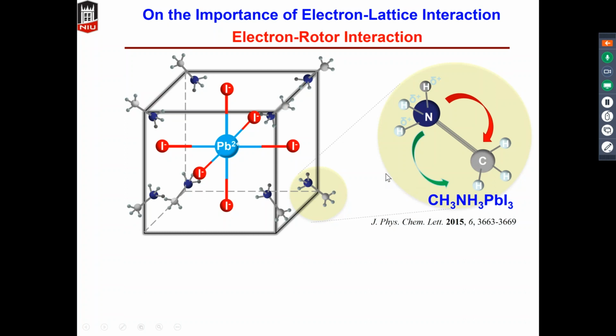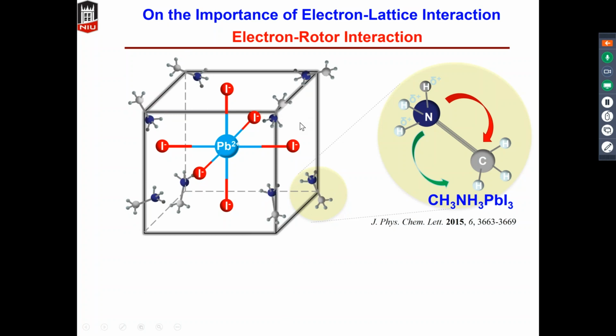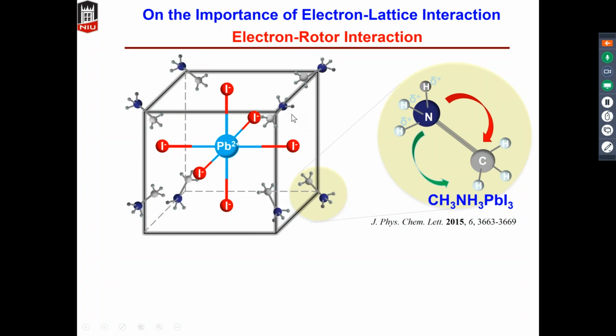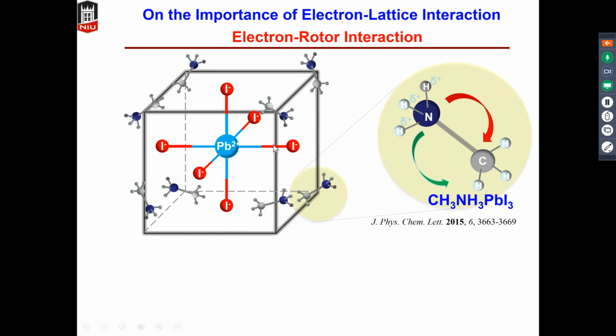cation. And a very interesting JPCL paper showed some experimental evidence that this cation is always in constant rotation mode. One along the CN axis, and the other one is actually out-of-plane rotation. Because this is an unsymmetric charge, the rotation of these cations will significantly change the local electric field.